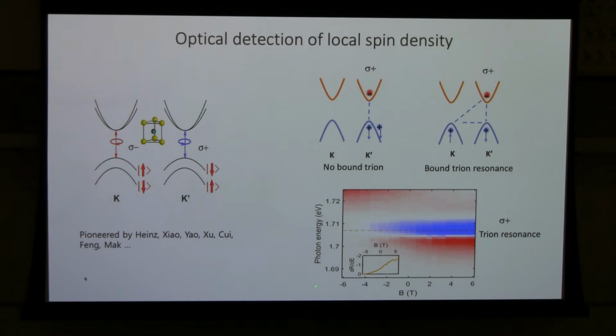For example, if you apply a positive magnetic field, you will align all the spins up, so all the holes will be at the K valley. If you use sigma plus polarization, you can see a very strong trion signal, and it becomes stronger when you have a larger magnetic field. But if you have the opposite magnetic field, the behavior is completely opposite. The negative magnetic field will push all the spins to be spin down, and then they will go to the K prime valley. In this case, it cannot form a bound trion anymore, so the trion resonance basically has zero oscillator strength. So if you use circular polarization to measure the trion behavior, you can tell the intralayer trion signal, and you can tell what the hole spin is.